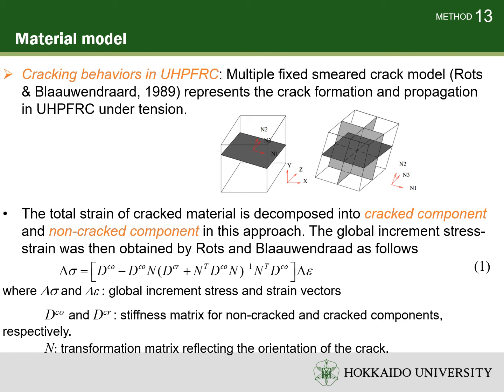Cracking behavior in UHPFRC. The multiple fixed crack model is used to represent the crack formation and propagation in UHPFRC under tension. Cracks initiate when the maximum principal strain exceeds the cracking strain in the direction perpendicular to the principal strain. Similarly, the second and the third crack initiate perpendicular to the first crack when the second and third components of principal strain reach the cracking strain.